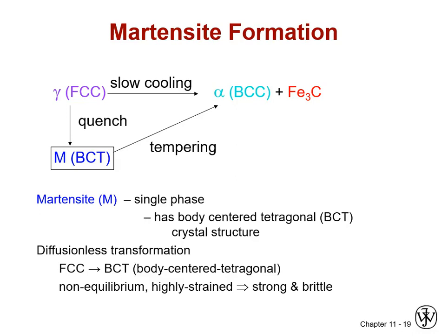We form a little bit of cementite, and we relax the strain energy out of that metastable structure. We get what we call tempered martensite. And without losing much in the way of yield strength or ultimate tensile strength, we regain a tremendous amount of fracture toughness. That is a treatment known as quenching and tempering, forming a tempered martensite structure.